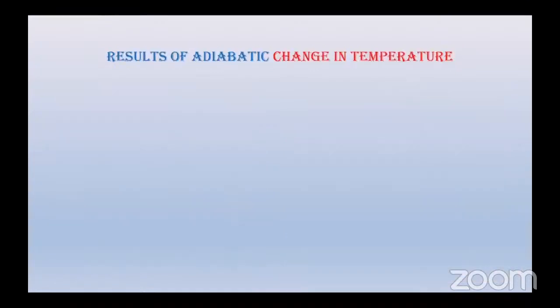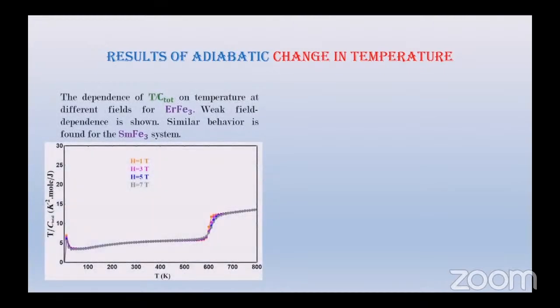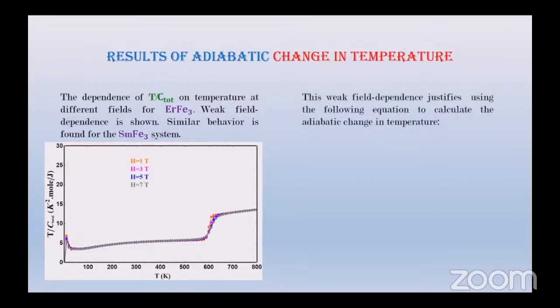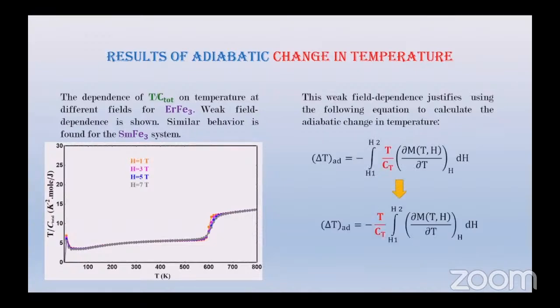Results of adiabatic change in temperature. The temperature dependence of T divided by the total specific heat at different fields for erbium iron 3. Weak field dependence is shown. Similar behavior is found for the samarium iron 3 system. This weak field dependence justifies using the following equation to calculate the adiabatic change in temperature.